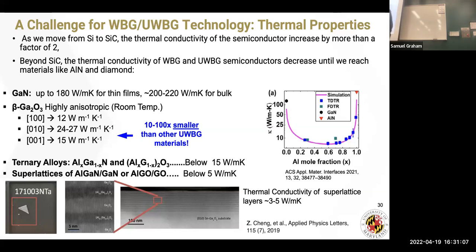But again, these figures of merit say that you should push towards these. The other thing that will happen is that sometimes you need to make layered structures. This is a layered structure of gallium oxide, aluminum gallium oxide. And so we start putting all of these interfaces together, and those interfaces can also impede heat transfer. We measured this, and you can see this is 3 to 5 watts per meter K. So there are people that throw their hands up and say, well, this is sort of the end of the story. Why go down this road? Let's move to something else.